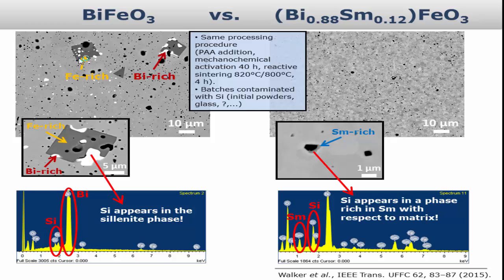And here is an experimental example, a comparison between 2 batches that were prepared in exactly the same way, in which we got some silica contamination. We still don't know the origin, but we found it by EDS analysis at SEM. Here in the case of BiFeO3, you see that we have plenty of secondary phases. We found the silicon basically in the gamma phase, and that confirms very nicely the phase diagram that I was showing before.